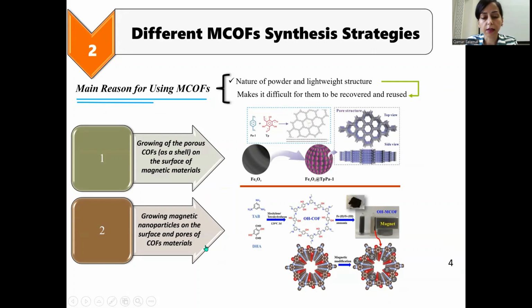In the second strategy, by growing the magnetic nanoparticle on the surface and in the pores of the COF material, we can achieve the final product. In this strategy, since the raw materials for synthesizing COF have a very low density, by using only 5 to 10 weight percent of magnetic material, we can achieve a very low density magnetic COF at the final stage.